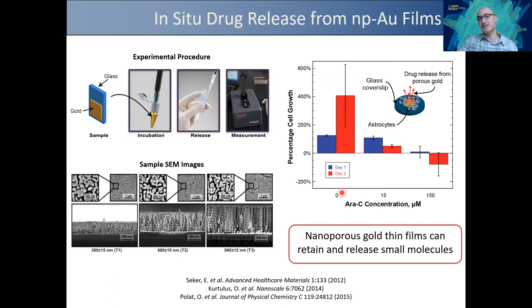So zero is vehicle, where it's basically just loaded with PBS, and the other ones are loaded with the drug molecules. As you can see, as you increase the drug concentration, astrocytes can no longer spread on the surface. If you increase it too much, then it becomes toxic. So this was a demonstration that you can load biologically relevant molecules and release them over time.